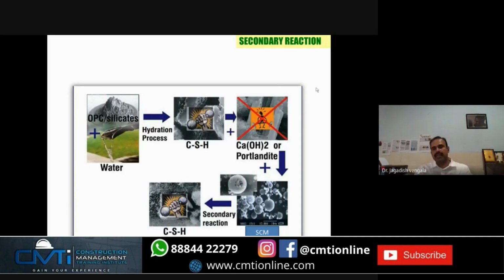What exactly is the reaction that happens by adding these supplementary cementitious materials? When you add water to ordinary Portland cement, we all know the hydration process happens. The final end product is what we call calcium silicate hydrate. Slowly the reaction happens and the CSH gel keeps forming. Along with that, there is excess calcium hydroxide, lime, present in the mix. When you add a supplementary cementitious material, either fly ash, GGBS, metakaolin or silica fume, it reacts with whatever excess lime is there. That means a secondary reaction happens and forms further calcium silicate hydrate, CSH gels, which is the main part of the concrete, which gives the strength